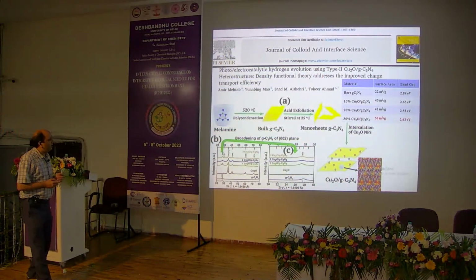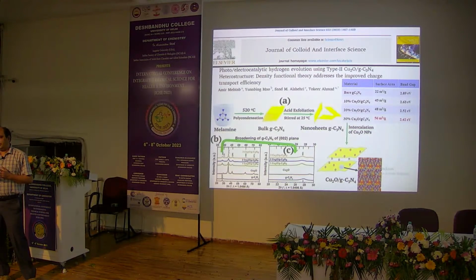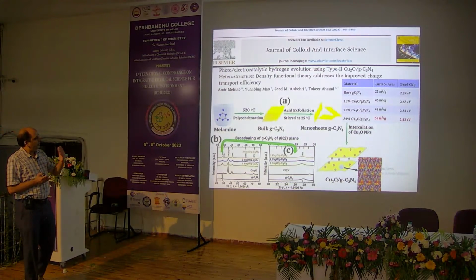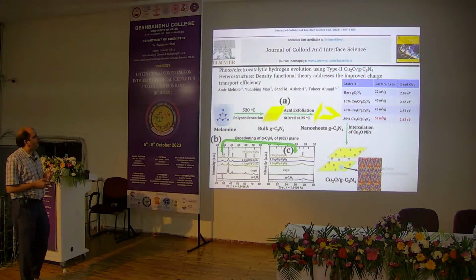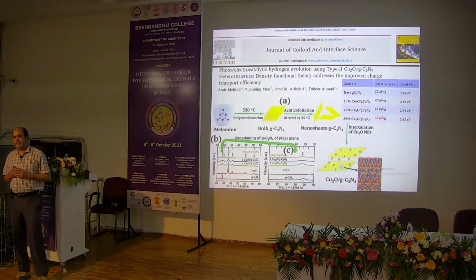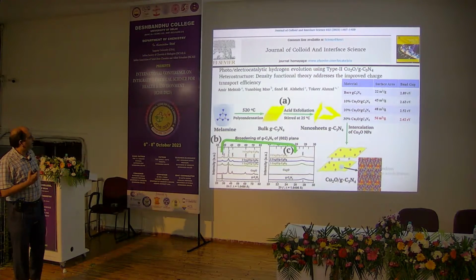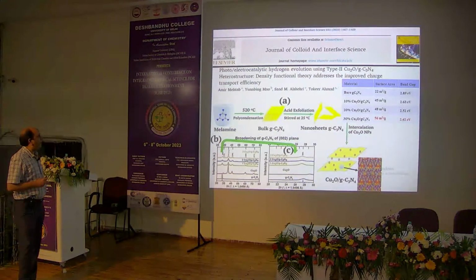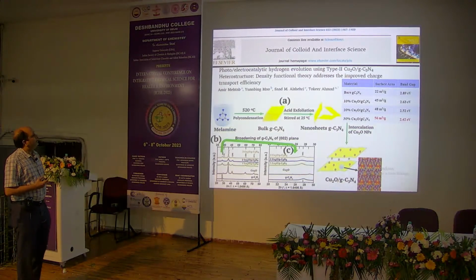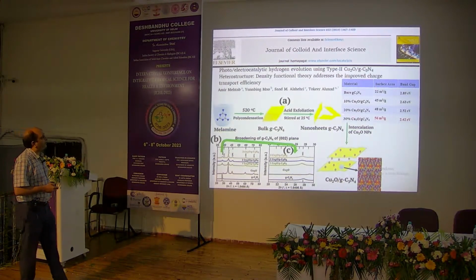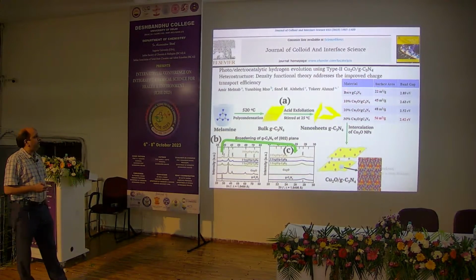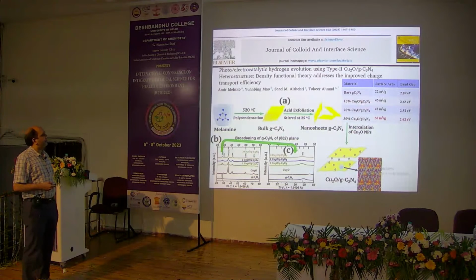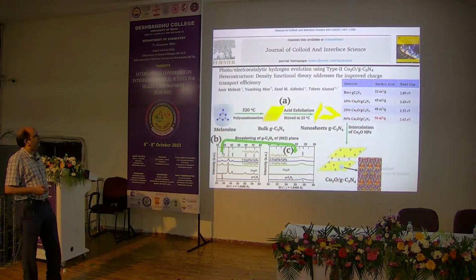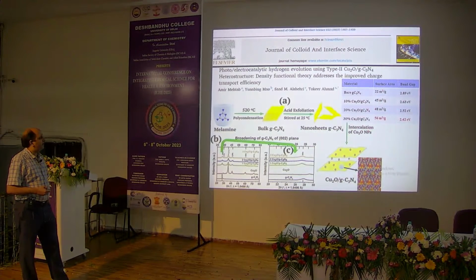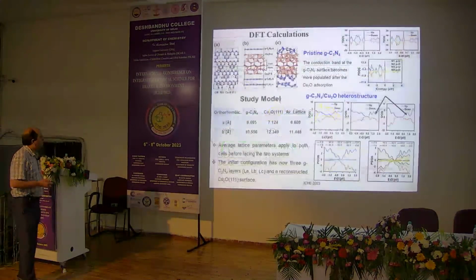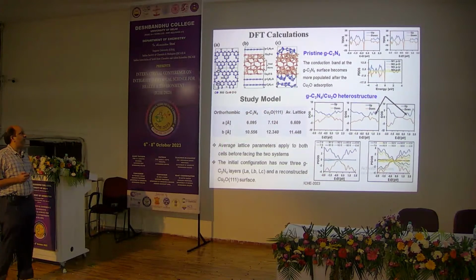Then this is the copper oxide graphitic carbon nitride heterostructure. Here we prepared the graphitic carbon nitride using the same methodology as we discussed earlier, and the copper oxide using a simple hydrothermal method. Then we prepared the heterostructures of copper oxide with graphitic carbon nitride in three different ratios: 10 weight% loading of copper oxide over graphitic carbon nitride, then 20 weight%, 30 weight%, and these are the basic investigations. Then this is the theoretical investigation.